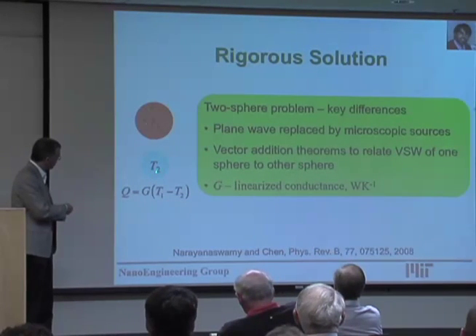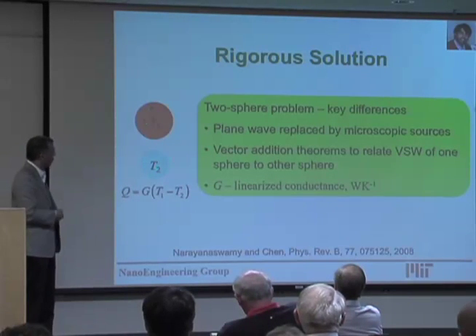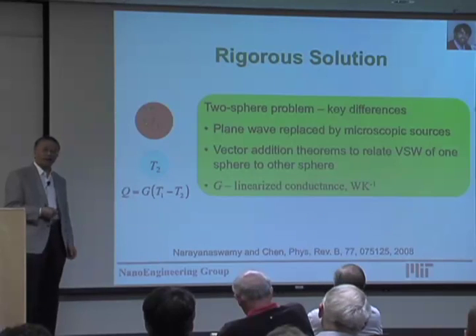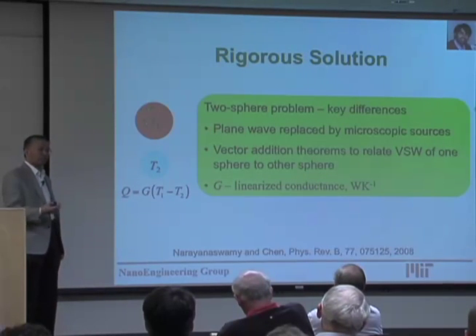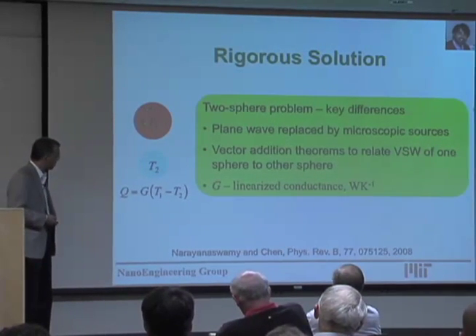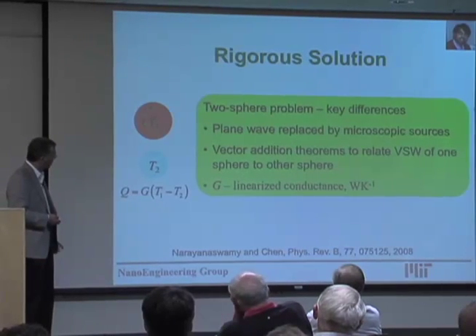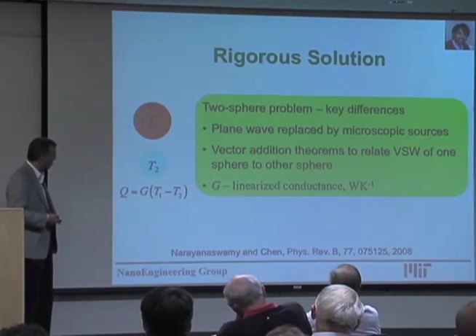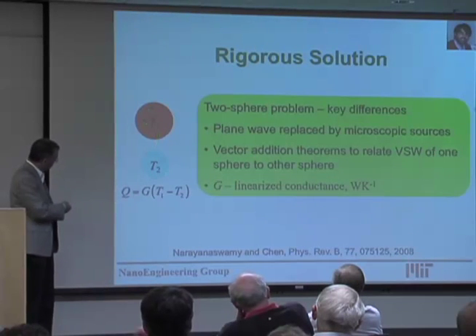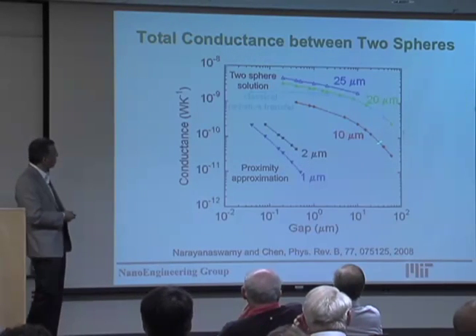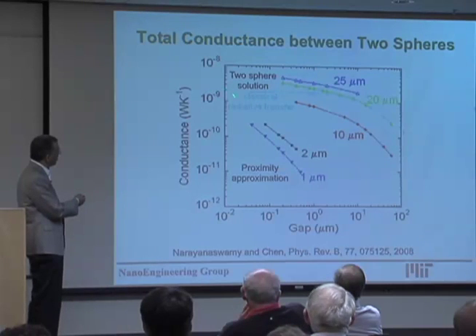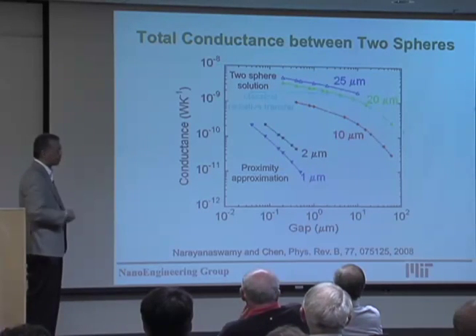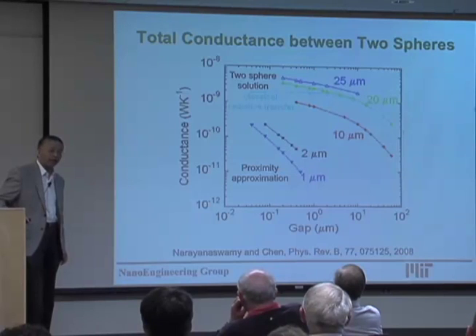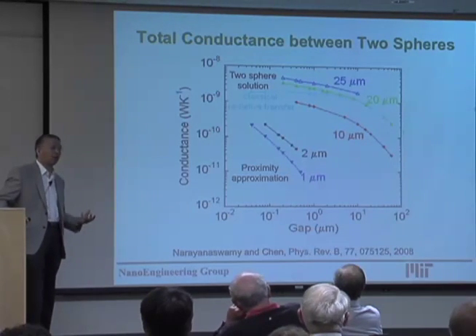So the first thing we did was some calculation. It's easier to calculate two spheres. Later on, a lot of people jumped on calculating the sphere and plate, which is really difficult from an electromagnetic wave perspective because of the geometric asperity. But we first did the two spheres, and our calculation shows this is the sensitivity range we need. We need about 10 to the minus 8 watt per Kelvin. So basically, we need to measure heat flow in the nanowatt regime.